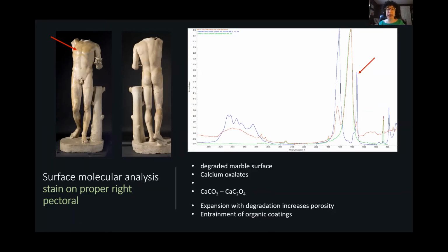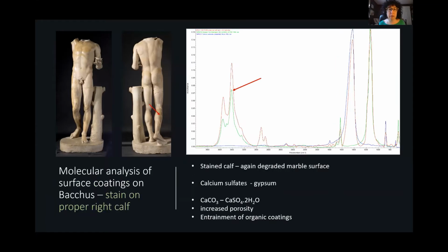And what I'm pointing at here with the red arrow is that we can see on the pectoral area not only the expected calcium carbonate, but also that a calcium oxalate film has developed there. So of course, when we go from the carbonate to the oxalate, the surface is going to expand, become even more porous, and the entrainment of these degraded organic films is going to become even more problematic, which gives us evidence of what our stain is made out of.